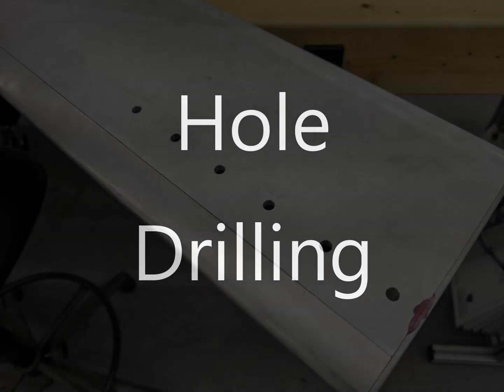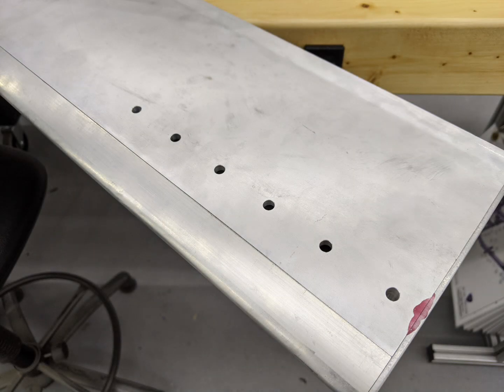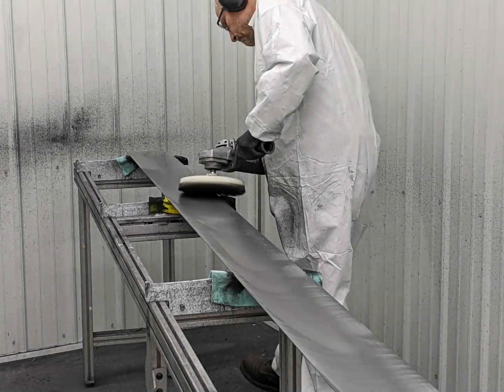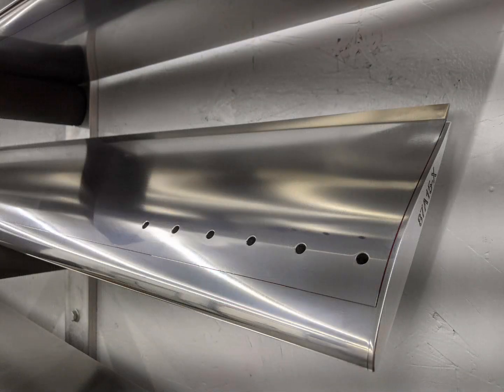With the coupons confirming that the cure cycle was successful, the blades can be removed from the oven, and we can add the holes that will allow the blades to be attached to the hub bar. Now we can move on to the polishing phase. After light sanding and then progressing through a series of polishing compounds, blades end up with a beautiful, smooth luster.